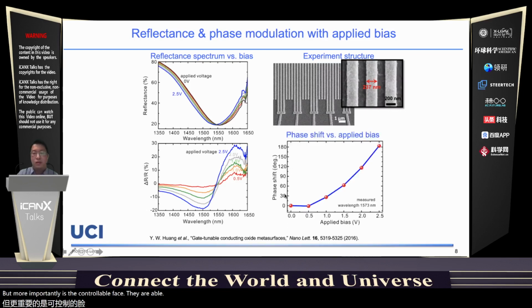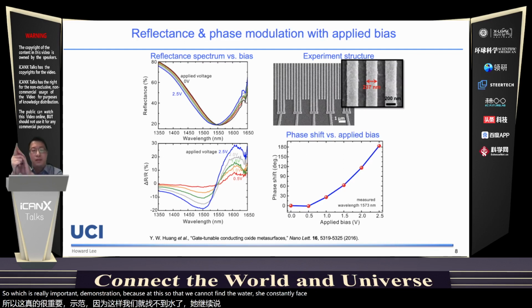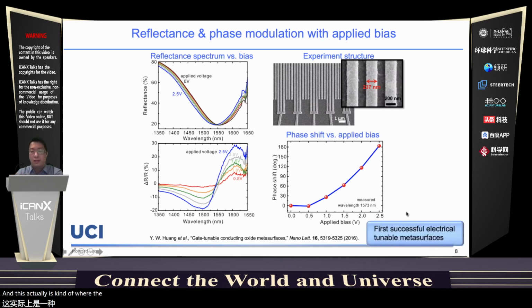We are able to demonstrate a phase shift of pi by applying a couple of volts. This is a really important demonstration because it shows that we can apply voltage to control the phase and amplitude of this metasurface. And this is actually the key for a tunable metasurface: to control the phase and amplitude. This is the first successful electrically tunable metasurface we were able to report at that time.